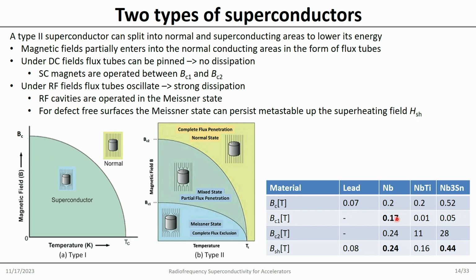So this BC1 is very high. This is the highest of every element, of any material, actually. So there's 170 milliteslas. And this is where we need to operate. We need to operate in the state where no flux tubes are in there. You see, for a material like niobium titanium, that field is very low. So it wouldn't be interesting to build an RF cavity out of that. So this is niobium, and here this is niobium titanium. Okay, for a wire it's fine. It can go up to 11 teslas or something.